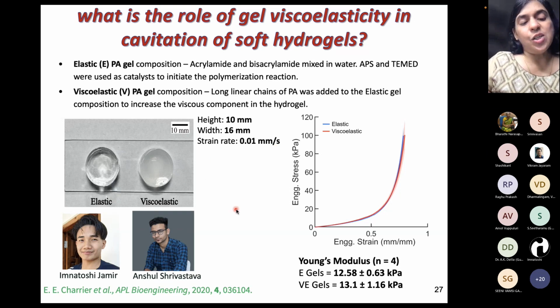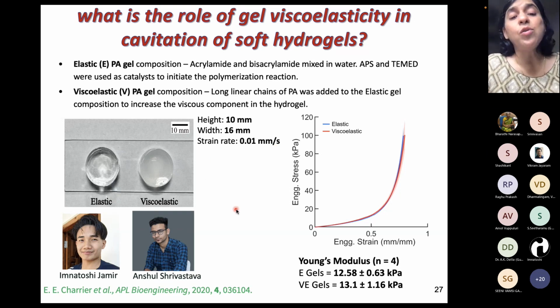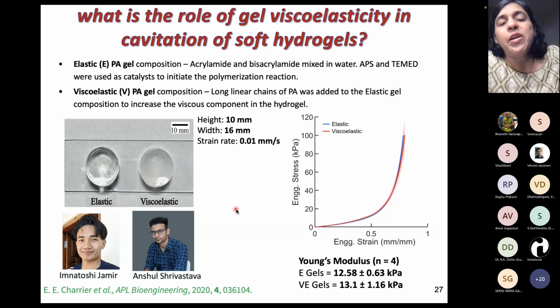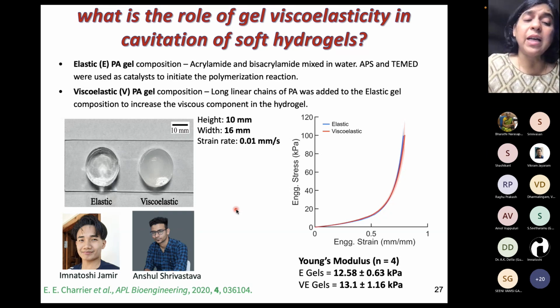It took us a few iterations, and this time we didn't want to work with gelatin because of the standard issues of not having proper control on the various parameters to give us more standardized results. So we decided to go back and look at polyacrylamide, which is a nice synthetic polymeric material. It can be made soft and stiff, and in a lot of our other work in mechanobiology, we use polyacrylamide very routinely to make 10, 20 and 30 kPa hydrogels that we study.